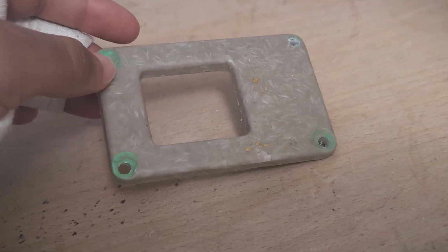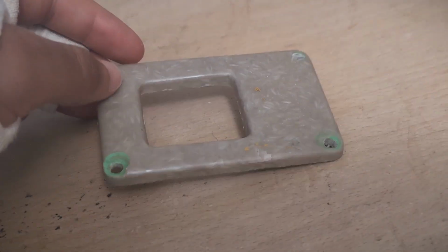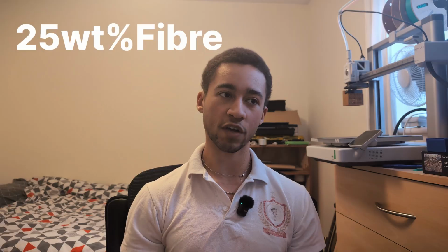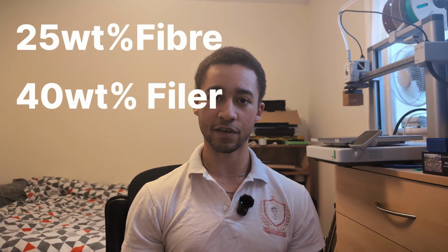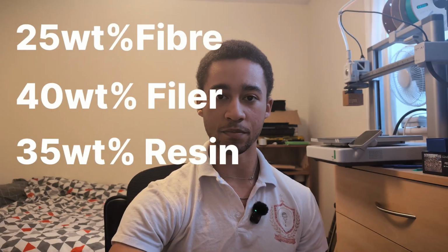So for this part, which is kind of my most successful part, it's just a kind of lid for something. I've settled on a fairly safe composite of 25% fiber, 40% filler, and then the rest resin. So you'll notice that is a 65% solids content, which is actually higher than in carbon fiber, where you typically use around 60%. In future, I kind of want to see how far I can push the fiber content, see if I can get to 30% or higher.